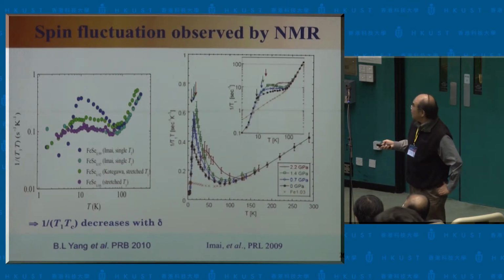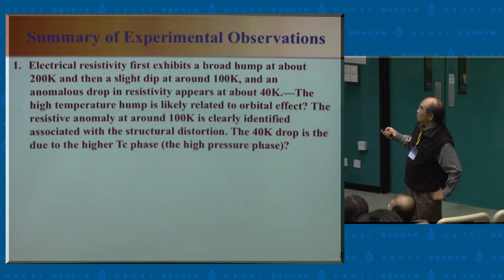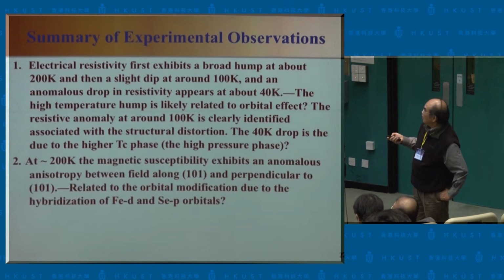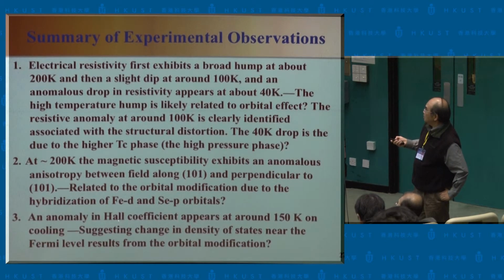Okay, so let me give a quick summary of what we saw. All this experimental data shows that the electric resistivity first shows a broad hump at about 200K, then a slight dip at 100K. And I mentioned this 100K is clearly associated with the structural distortion. And of course, there's the 40K I mentioned earlier. The magnetic susceptibility at 200K also exhibits an anomalous anisotropy between field along 101 and perpendicular to 101. We think that has something to do with the orbital effect. And an anomaly in the Hall coefficient at this temperature indicates a changing density of states near the Fermi level.